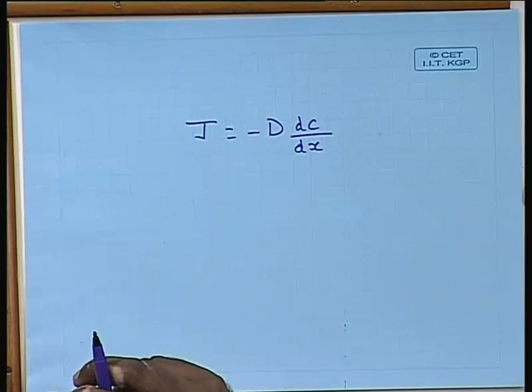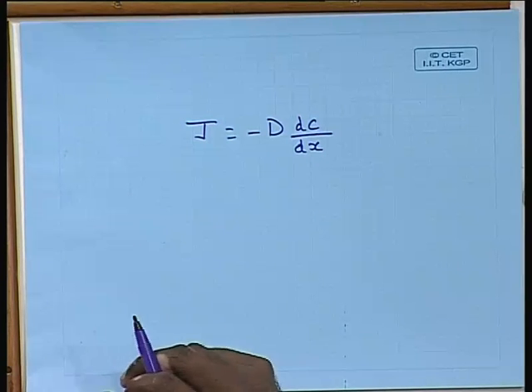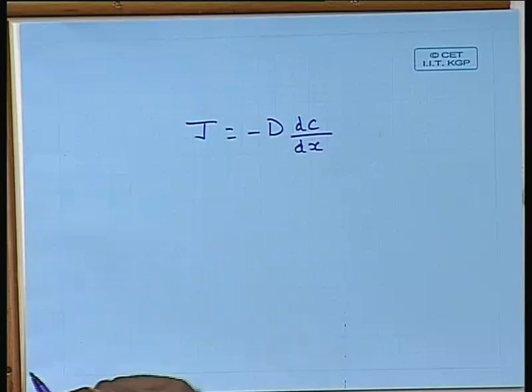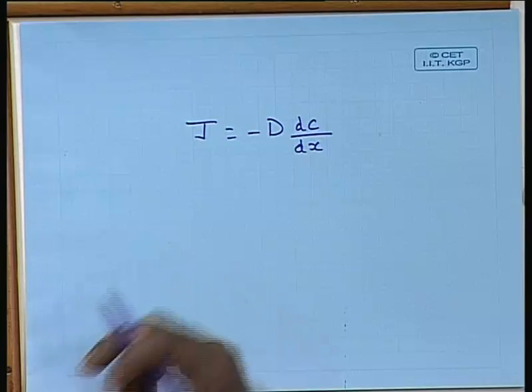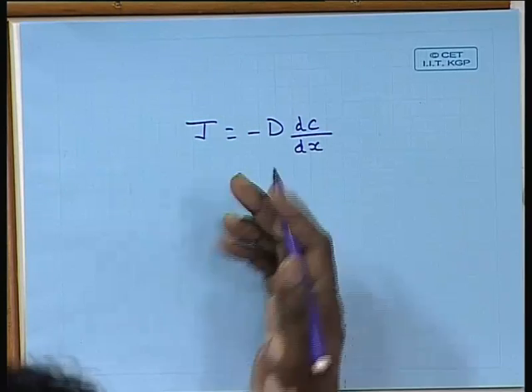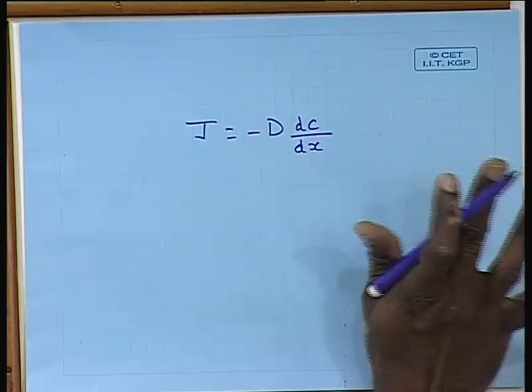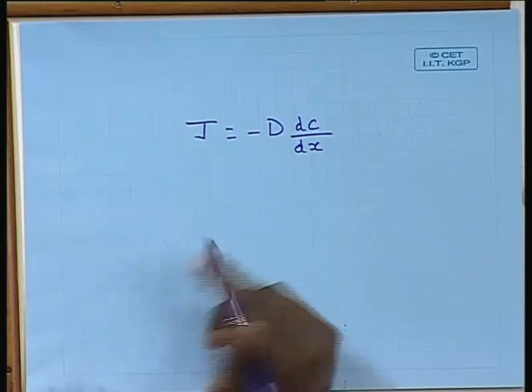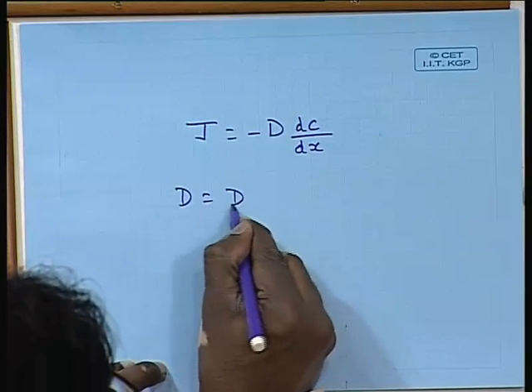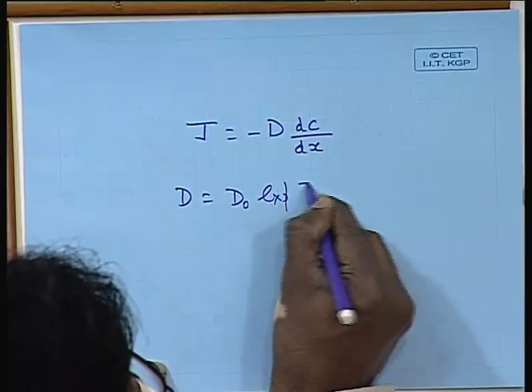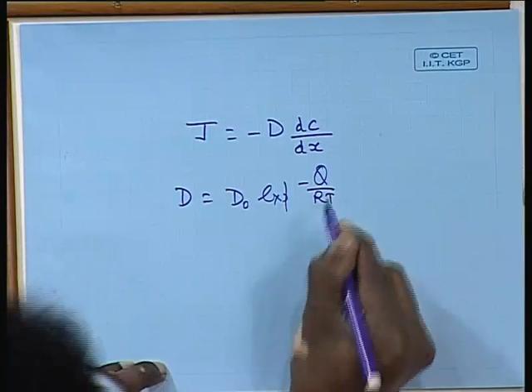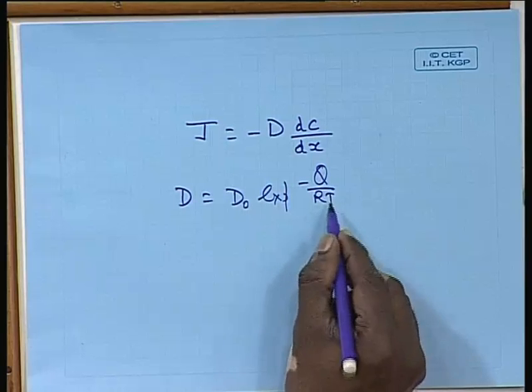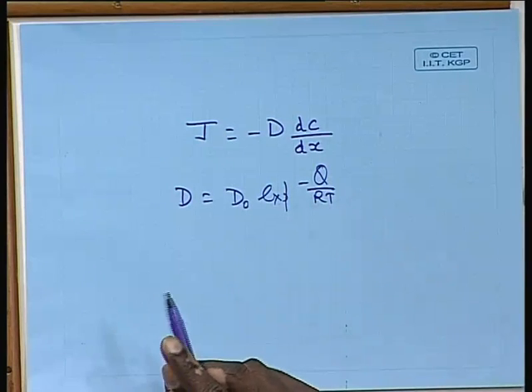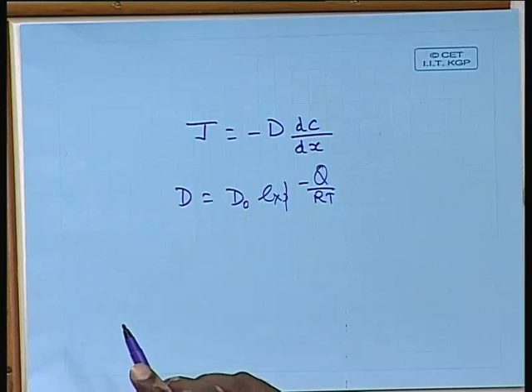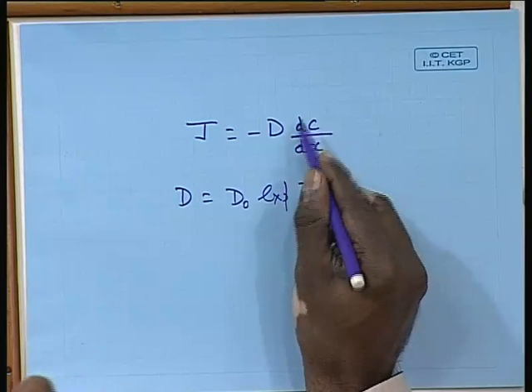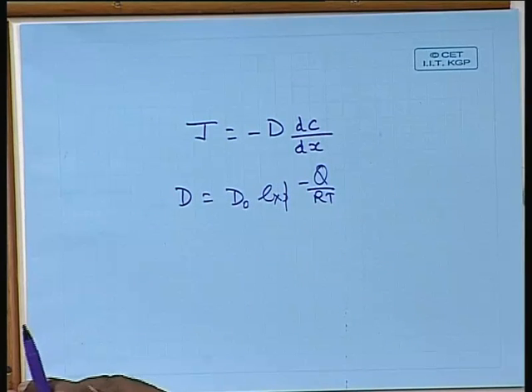All of you have gone through a diffusion course at some point of time, or as a part of some metallurgy course you must have come across diffusion. Anyway, Fick's laws you must be aware of. So basically diffusivity is more or less taken as a temperature dependent process, where D is equal to D naught into exponential minus Q by RT. So where temperature comes into the picture, Q is called the activation barrier for diffusion and D naught is what is called the pre-exponential factor. So now dC by dx is very crucial in this kind of situation.